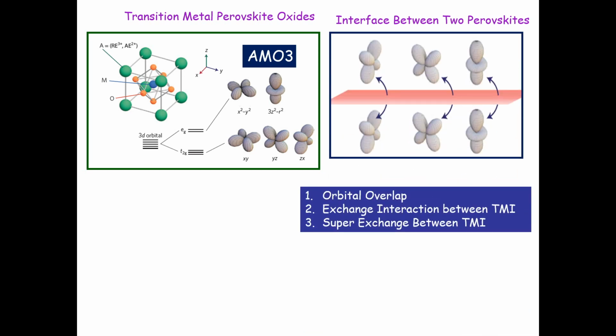Now I go ahead and make an interface between 2 different perovskites. On the top I have one kind, below I have the other kind. If the interface is very, very clean, you can have direct interaction between these orbitals, so direct exchange interaction between transition metal ions. And that can lead to new magnetic states at the interface. You can also have this interaction mediated by oxygen at the interface. Then that becomes a case of super exchange between two transition metal ions through oxygen.